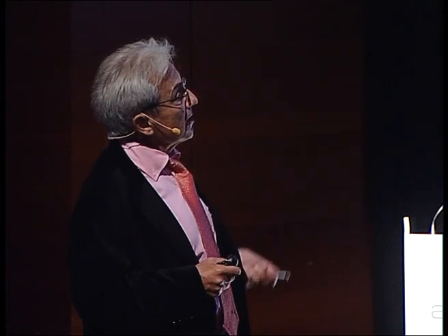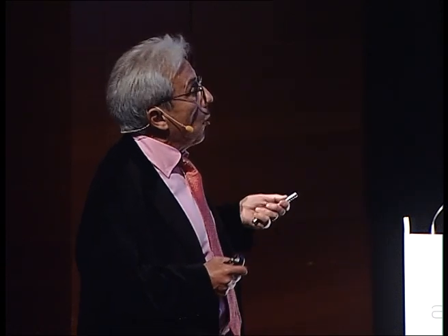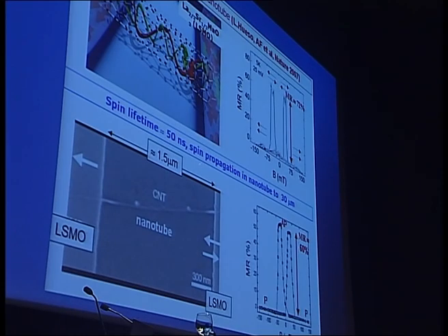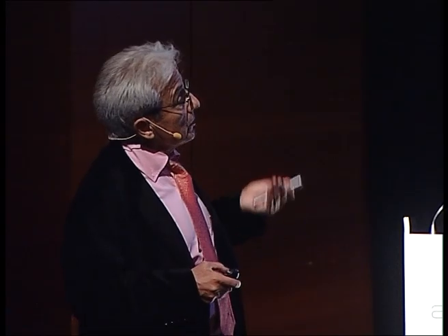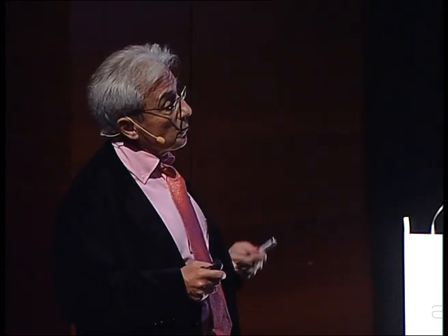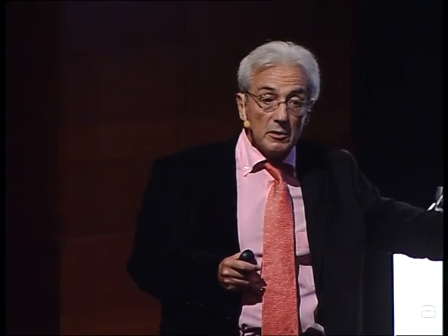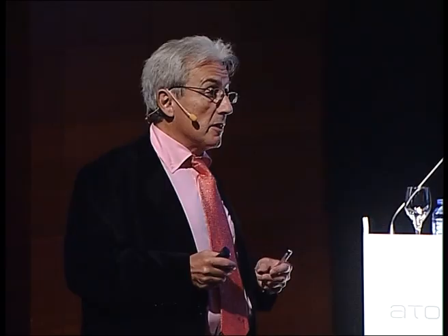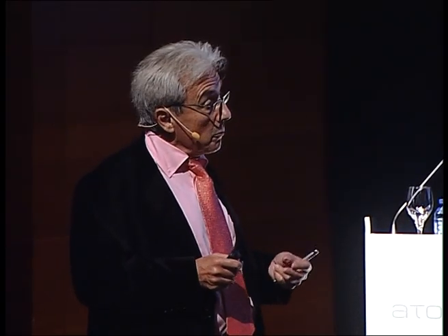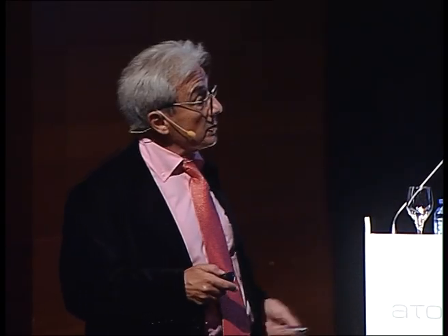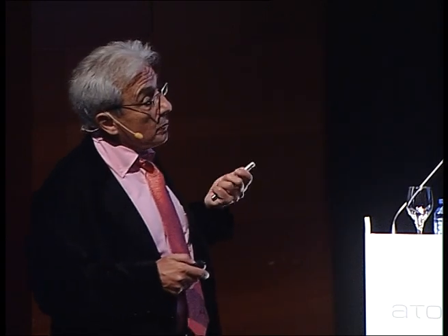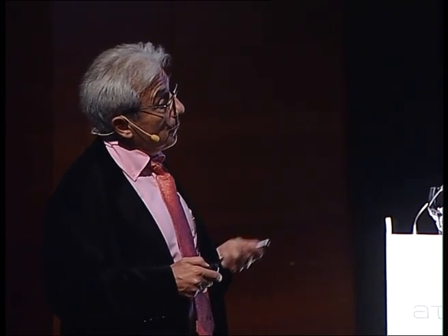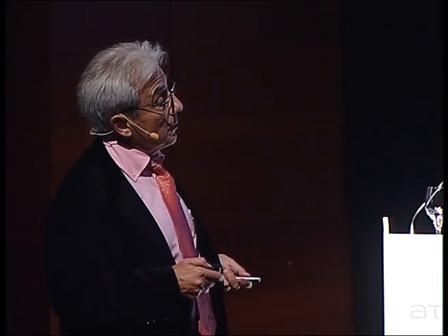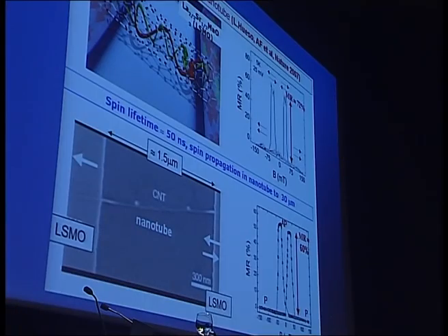Okay. For example, in the experiments, the spin lifetime is long, 50 nanoseconds, and finally, the spin propagation in the nanotube can be about 30 or 40 microns. And so it's interesting to have materials like carbon nanotube or graphene in which a spin can propagate to this long distance. There is a possible space for several logic gates, for example, on this distance. And there are several concepts that can be imagined by using this spin propagation to long distance in this material.